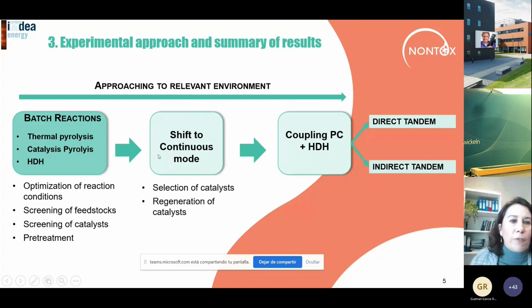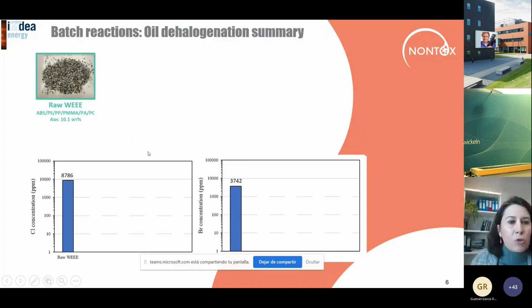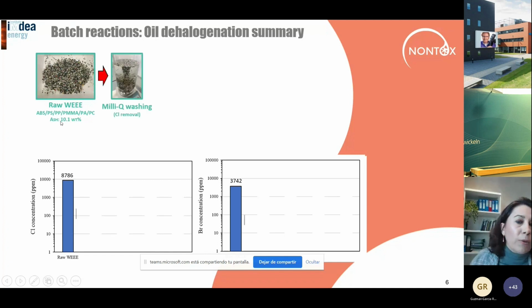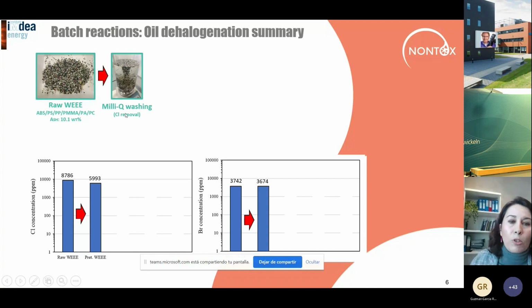Just starting with the first step, this is the summary of the results that we achieved. First, for example, with a sample such as this one, a raw material from electronic wastes with a very complex composition and even having some ash, we determined that applying a first washing with water, we could remove an important amount of chlorine, not in the case of bromine, because bromine is in the form of organic compounds and it is not soluble in water. But in the case of chlorine, some of this chlorine is in the form of salts and can be removed by this washing treatment.